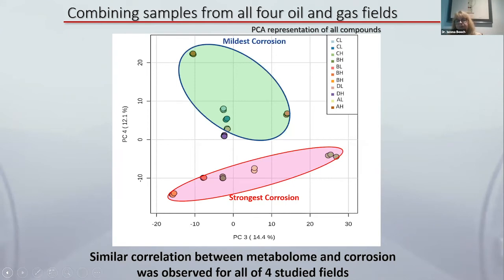And it's been reported many, many times. And I've seen it myself, that it was the material that was selecting the population. It was the material that was selecting the corrosion behavior of this population, and temperature, which was very, very important, but not so much the geographic location of where this corrosion failure was taking place. And I've seen that on copper nickel alloys, and I've seen that on different types of stainless and carbon steels.